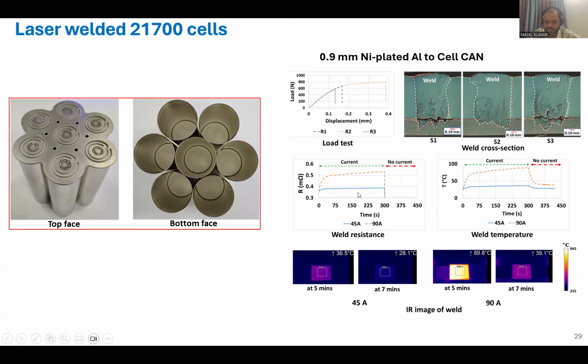This is the current carrying capacity. I have shown how much current can be passed. If you go for 90 amps, there is a very high temperature rise. So it is suitable for 45 amps maximum, because companies are asking for 15C or 10C current. That's why I did this testing at about 45 amps to check the 10C of this cell.